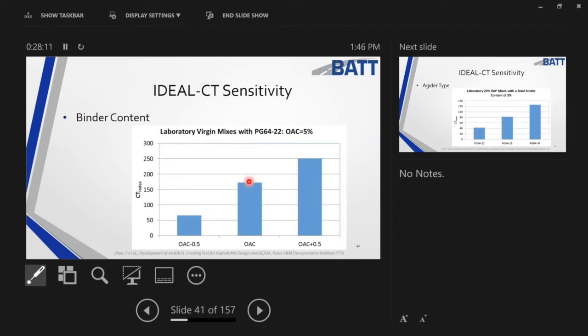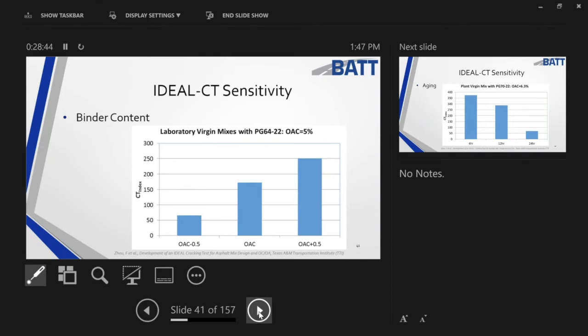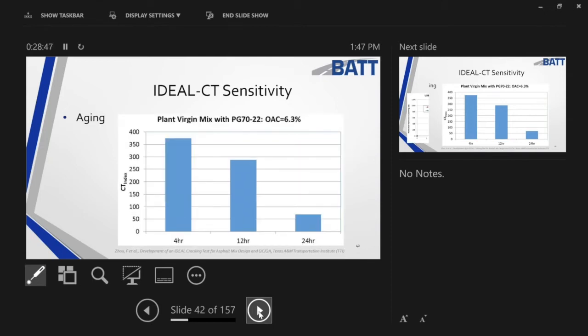Now, OAC stands for optimum asphalt content. And so Fuji took that same number. Joe had his laser there on in the middle, and he went 0.5% below, 0.5% asphalt below, and then 0.5% above. And look what happens. We can go from a 60 to about 160, all the way up to 250. And I'm seeing that in my laboratory too. I actually saw values pushing in the 300 range here in Kentucky. Now, it was not very stable because it would not meet the rutting side, but I was able to push up to 300. So yeah, asphalt makes a big difference on that.